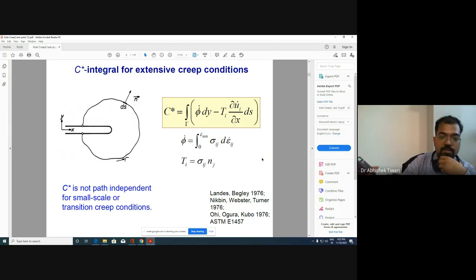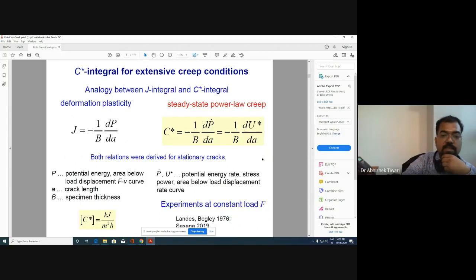Now here we see that the J integral is not calculated experimentally by doing that integration of phi dy minus traction vector into del u by del x ds. We don't do that. What we do is load a specimen, as you have seen in the video, find the force versus displacement data for different crack growth, and find the area under the curve of the force displacement, which gives us the strain energy somehow, and that is related to J. After doing a lot of mathematics, you will get this formula.